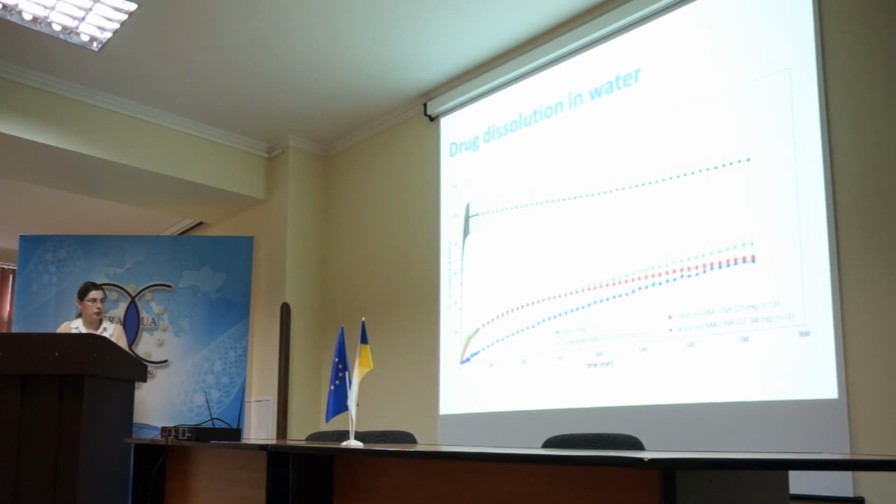Physical mixture and unwashed sample is similar with the pure drug, so it is also limited. When we apply the drug loading and washing, almost full amount of the drug is released, and it is done in the first hour. So this kind of nanocarrier improves the dissolution of the nimodipine.